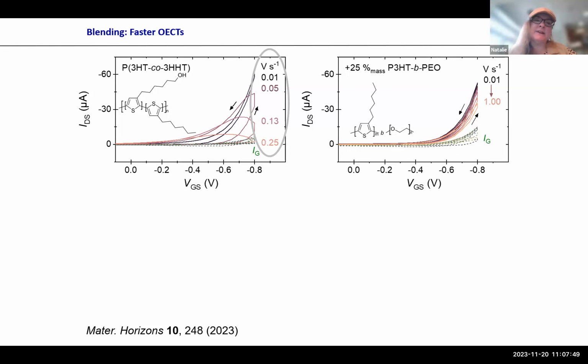Yes, and that's where the blends like PEO come in, because in principle it should be only the electronic charge carriers. But of course you change the environment because you get the electrolytes in, and you likely change, which was in my third part that I didn't have time for, the chain conformation, especially with flexible chain conjugated polymers, maybe not the rigid ones. That's why, like, Antonio's series on the N2200.